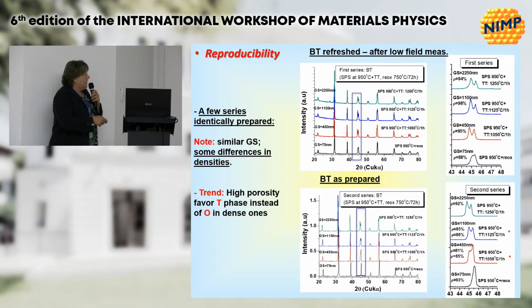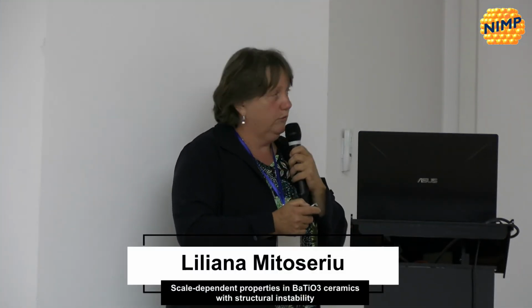And here I can show you a similar result from a different set of samples that we have prepared, but always from the same powder. The similar relative density shows the orthorhombic state like this one. While, for example, here, the 450 nanometer sample, if it has high porosity, is quite tetragonal, and if it is dense, it tends to become more orthorhombic, because the peaks are inverted between the red graphs here. What was nice to see is that we get the same grain sizes by the method, so we validated the reproducibility of grain sizes, but from one sample to another we had a variability of porosity, and that's why I decided to report only the dense one.